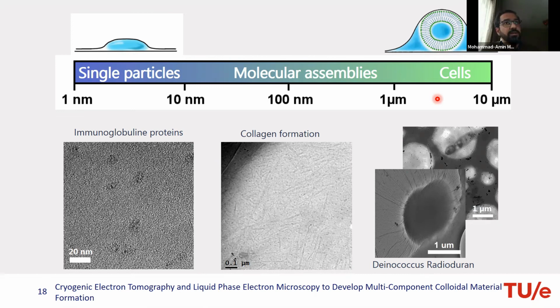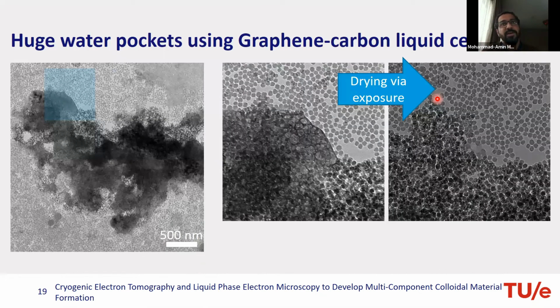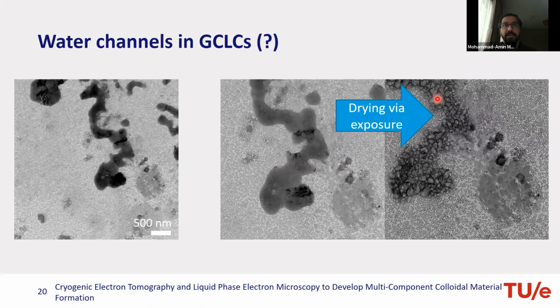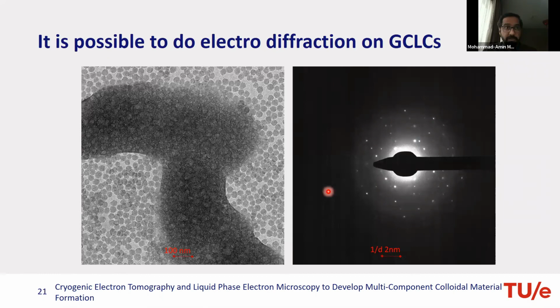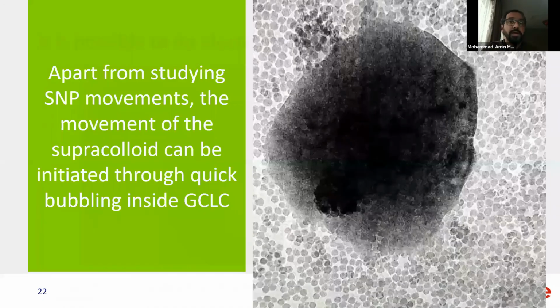Very recent experiments that I could do despite the corona time show that if we replace one of the graphene layers with carbon, we can actually make huge water pockets. And if we do surface treatment a little bit, we can make channels of water, and you can compare these really huge channels with what we had before. We can still follow up processes with electron diffraction analysis, and a very surprising moment or experiment was that